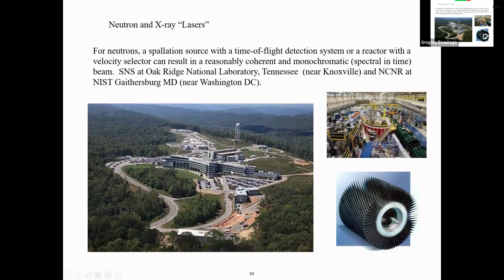The nice thing is that hydrogen and deuterium have the largest difference in contrast of any materials on the periodic table, and they have identical chemical nature. So you can take a hydrogenous polymer and make it with D2O instead of H2O, and you have a deuterated polymer. You can mix 1% deuterated polymer into a hydrogenous matrix, and then you can see a single chain in a melt, say under shear. It allows you to light up a single chain, with exactly the same behavior as the hydrogenous chain. So there's a huge advantage to that.